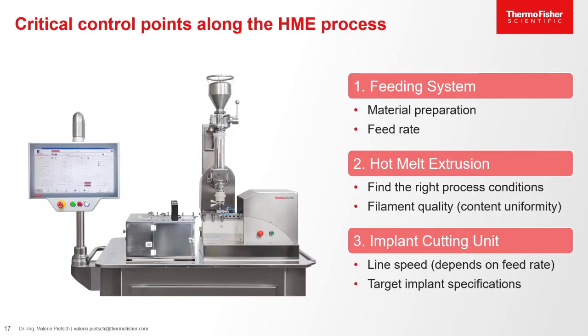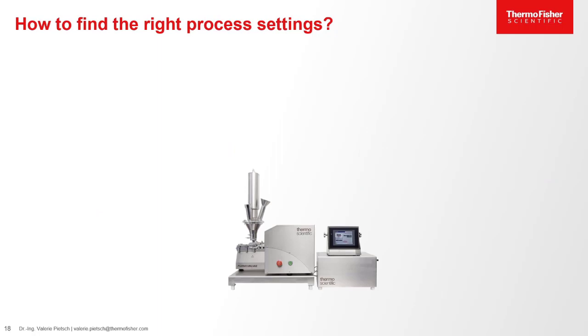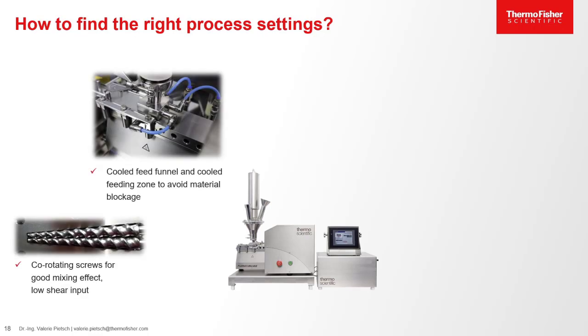Now let's go on to the second control point, the hot melt extrusion process. When it comes to that, we usually work with our Pharma Mini HME, which is a conical co-rotating twin screw extruder. The co-rotating screws we usually use to make sure that we have a good mixing effect, not too high shear input, to make sure that we don't degrade our API. And also the conical effect allows us to have a system that runs with almost no pulsation, which is very important to get a constant strand diameter.